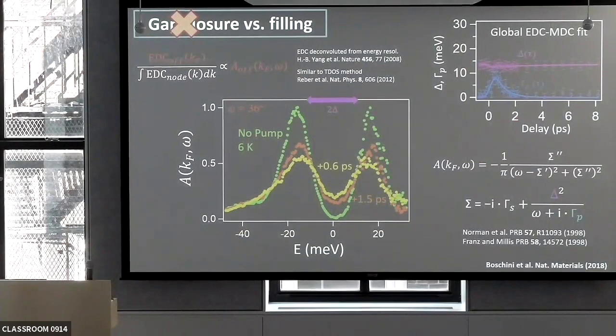And as you go to high fluence, then you start seeing bigger changes everywhere, and eventually the gap is completely gone. But even if you go to a fluence where you have an almost complete filling of the gap, and the electronic temperature is similar to the one of TC, the gap is anyway reduced by 30%, while the filling is almost maximum. Then if you pump more, the gap is completely filled, and you don't see any other variation.